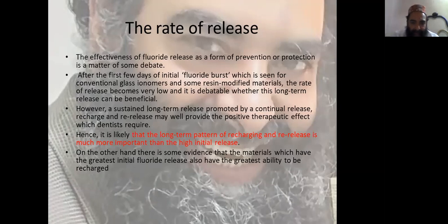However, a sustained long-term release promoted by a continual release, recharge and re-release may well provide the positive therapeutic effect which dentists require. Hence, it is likely that the long-term pattern of recharging and re-release is much more important than the high initial release. On the other hand, there is some evidence that the materials which have the greatest initial fluoride release also have the greatest ability to be recharged.